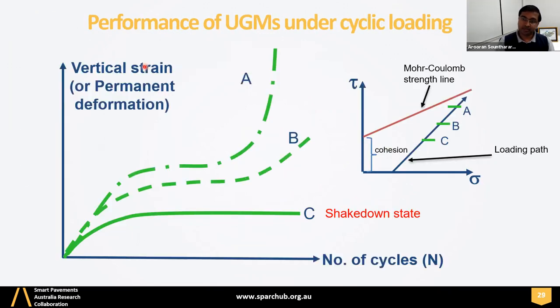So what happens as you go closer to the failure line? Here we are talking about cyclic loading, right, repeated cyclic loading as applicable to the real pavement in the field. So ABC denotes here. If we are far away from the failure line, the pavement, vertical strain, or in other words, rutting or permanent deformation with number of load cycles, reaches the shakedown stage. That means only the mode zero rutting, if you are in stage C, which is very far away from the failure state, and then it's stable there, just mode zero rutting.